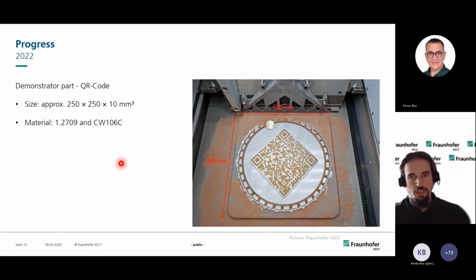Then we managed to get even bigger as we achieved our SLM280. So now we are able to build very large parts with, as you can see here, a side length of 280 millimeters by 280 millimeters. And you can also see that this is very clear, very sharp. So the resolution of the process is very high at the moment.